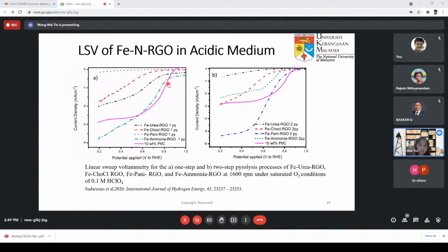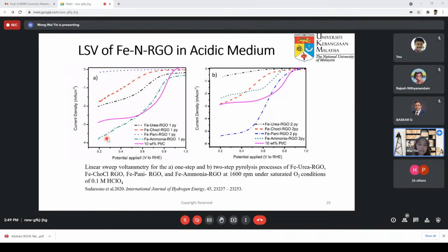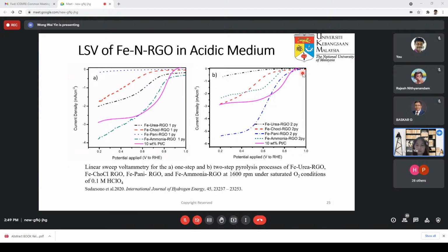And here, this voltammogram goes down without reaching a limiting plateau, which shows that on this catalyst, even though it shows good activity, the active sites are not uniform. We can also see that Fe-Pani is inactive, similar to the cyclic voltammetric analysis. Upon second pyrolysis, we see a drastic change in the activity for the Fe-Pani. Now it is actually the Fe-Pani which is the most active as compared to the rest. Of course, it's still slightly lower than Pt/C.